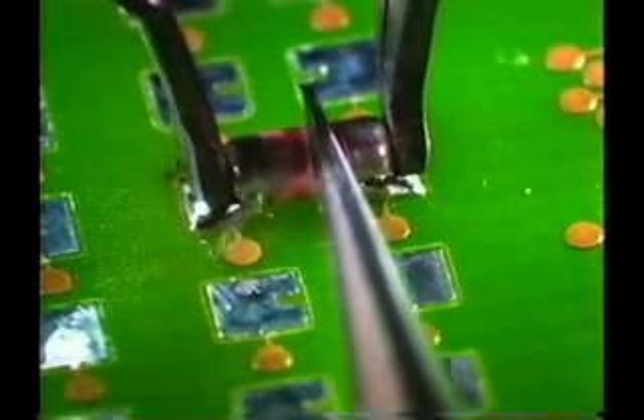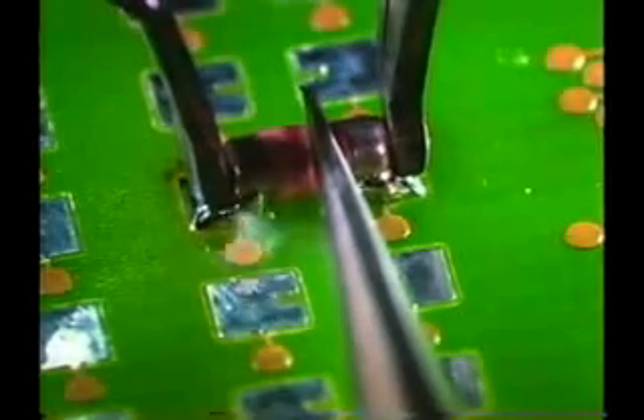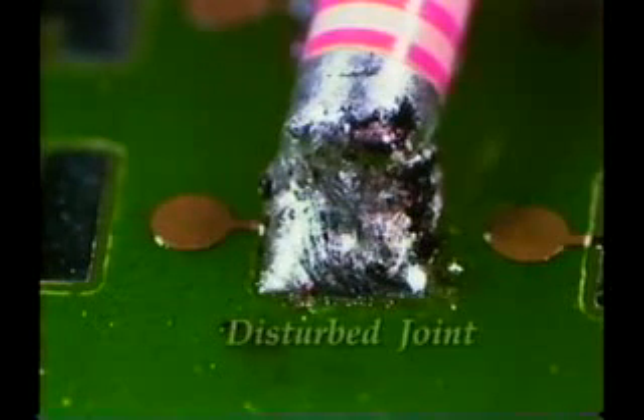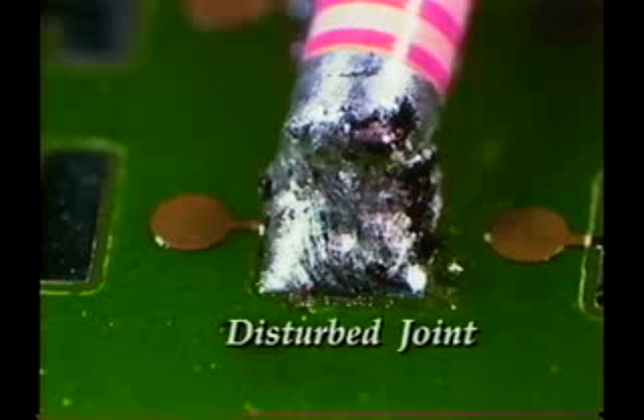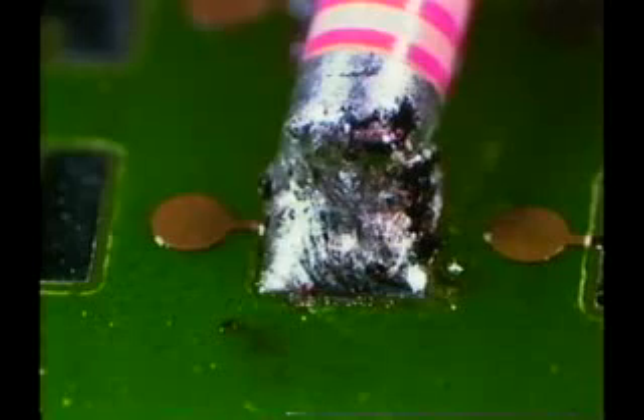Whenever you use a tool to hold a component in position, it's extremely important to keep it perfectly still during solder solidification. If the component moves even a slight amount during the hardening process, look what happens to the structure of the solder. This type of grainy texture is not just a cosmetic problem, it indicates the structure of the solder is disturbed and likely to fail.